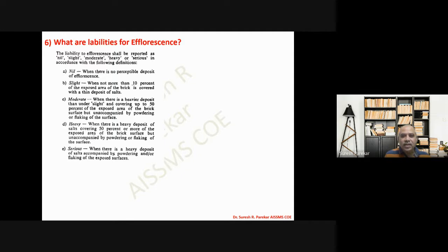Then moderate when there is a heavier deposit than under slight and covering up to 50%. So this is not more than 10%, slight, moderate up to 50%, heavy we have more than 50%, but unaccompanied by powdering or flaking of the surface. So this is not there. Powdering or flaking is not there. When there is heavy deposit along with powdering and flaking of the exposed surface, then that bricks are serious, and we have to think whether we have to use it or not.